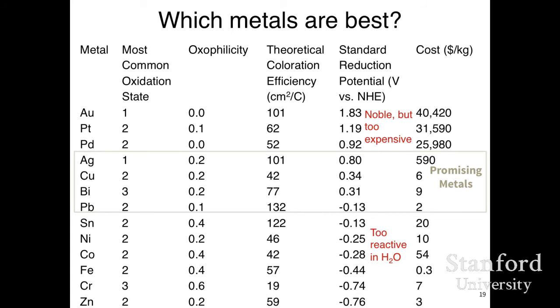We started with copper because it's well known that copper can be electroplated, and there's a lot of literature on how to do it. But copper by itself is red, so we needed to put another metal in there to get a neutral color. We started with lead because there's so much known about the electrochemistry of lead since it's used in lead-acid batteries. And we made great windows, but the early feedback we got is that it was a non-starter to have lead in these windows.